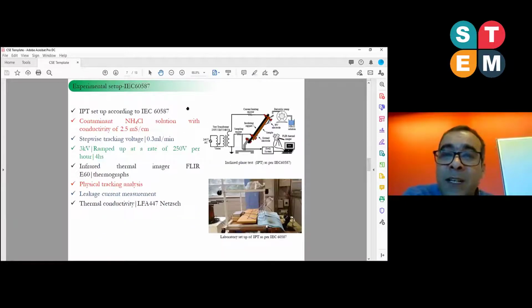So this is the experimental setup according to 60587. In 60587, we have to mount the samples on an insulating support. That is the insulating sample here. Second, we have to apply the high voltage with a test transformer. How much high voltage we apply, and what the flow rate of the contamination solution will be, is defined in the standard. So we have to follow all the instructions according to the standard.